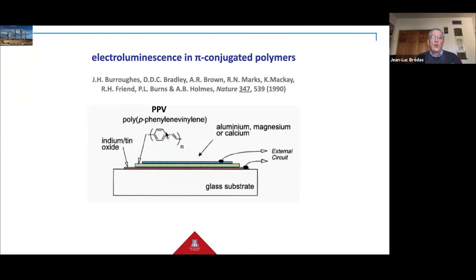polyphenylene vinylene, which was discovered as being electroluminescent by the groups of Richard Friend and Andy Holmes at Cambridge back in the late 1980s. And this gives us also the most simple architecture in the case of an OLED. You have, of course, a transparent substrate, a transparent anode, in most instances indium tin oxide, a thin layer of the emitter, in this case PPV, and then a low work function cathode.